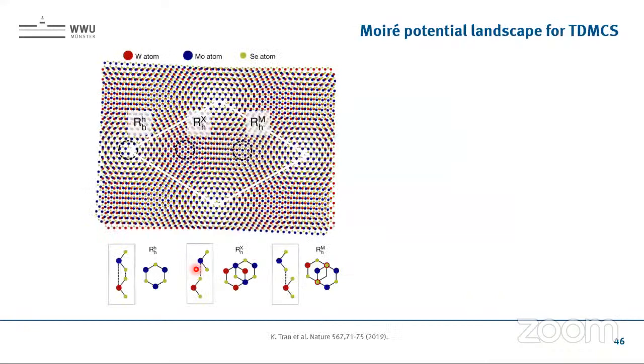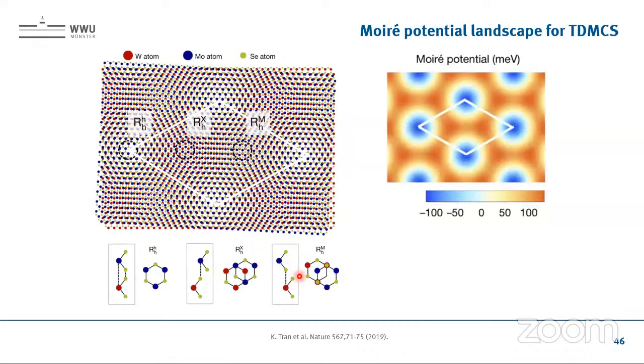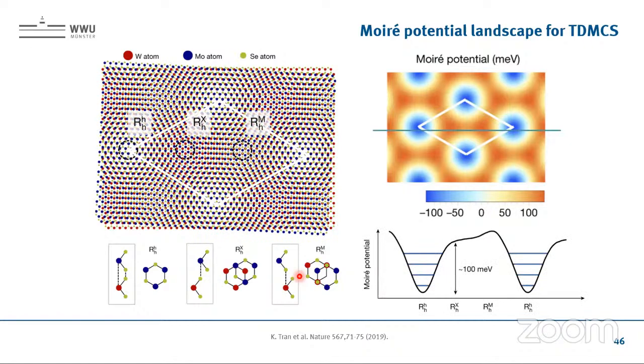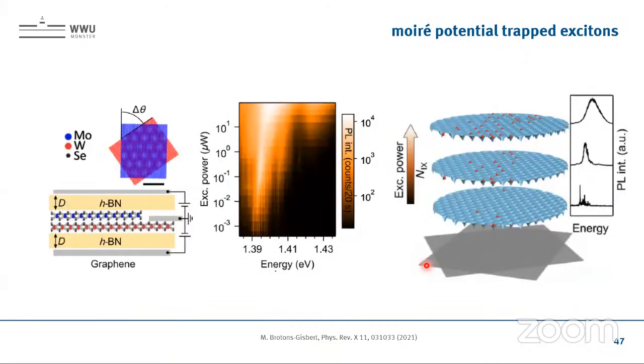So for the geometrical effect in real space, due to the different registries, if you go to these different sides of this moiré potential, where different atoms are lying on top of each other, you get a moiré potential landscape, also in the single particle energies. And it looks like this, where you have this kind of quantum confinement, like little puddles, holes, where we have discrete states, and these discrete states can be seen like quantum dots, where excitons can be confined, and that's a measurement of energy versus excitation power.